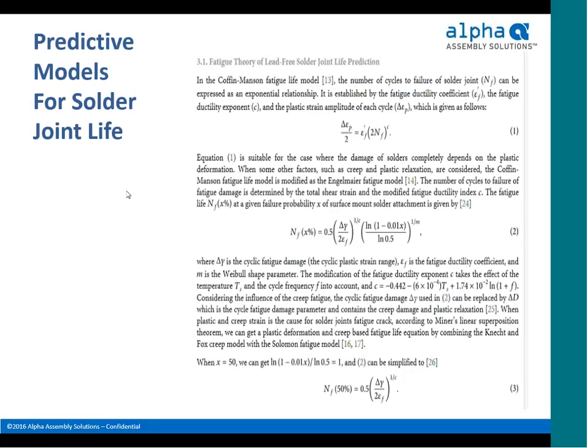This is where the industry was pretty well established for tin lead. There was a pretty high level of confidence in the predictive models for solder joint life, the acceleration factors, the effects of different conditioning on the end result of the test units, and the relationship between that and full service life in hours or cycles or miles or whatever the unit might be. However, we're still gaining a lot of that data in the lead-free world because we're now starting to approach the end of life for some of the initial generation RoHS compliant products in field service. Until that loop is closed, we won't be able to really get a good idea of how well correlated these current models are.